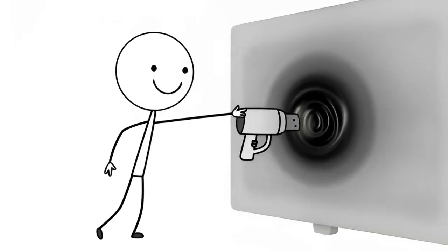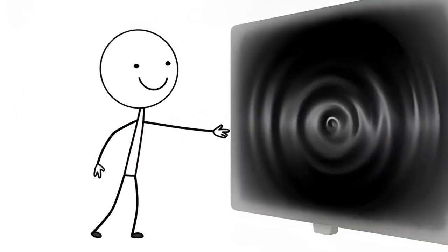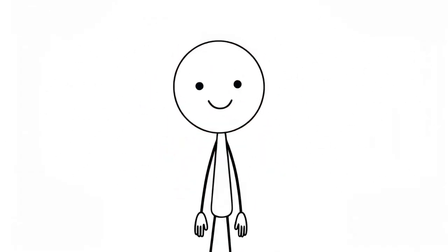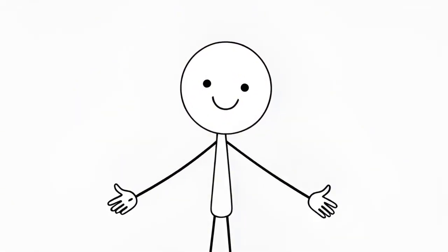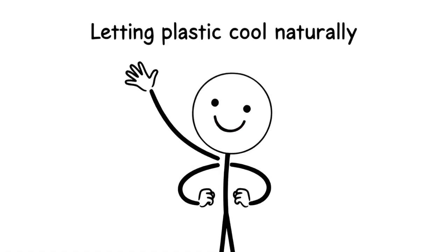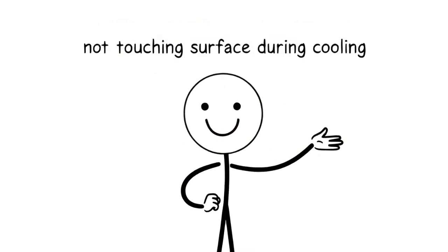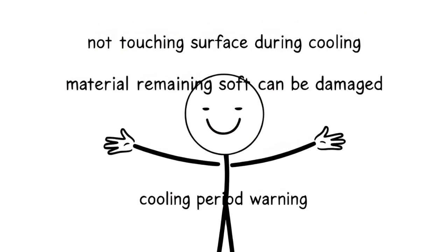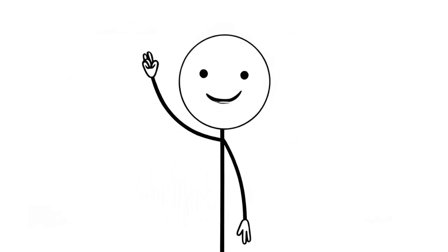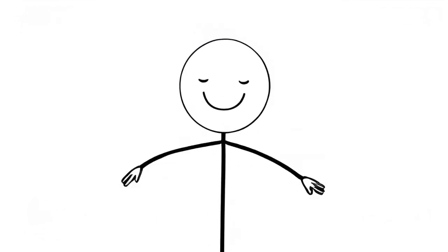You will see the gray color darken to black in real time as the heat activates plasticizer migration. The transformation happens within 5 to 10 seconds of heat exposure per section. Continue until the entire faded surface has been treated. Let the plastic cool naturally for approximately 5 minutes. Do not touch the surface during cooling as the material remains soft and can be damaged. The restored black finish is permanent and requires no sealing or top coat.